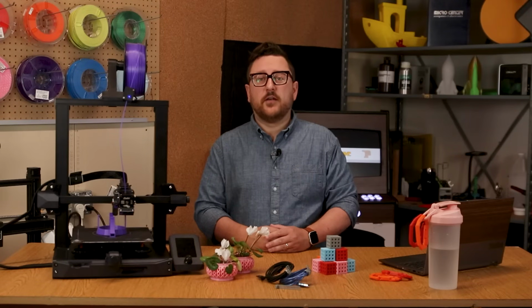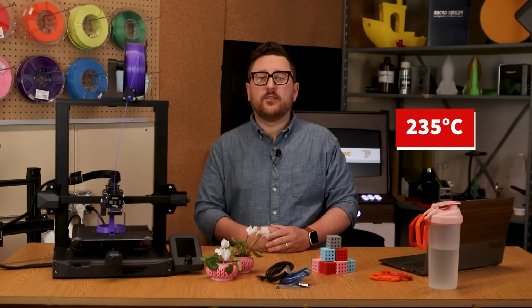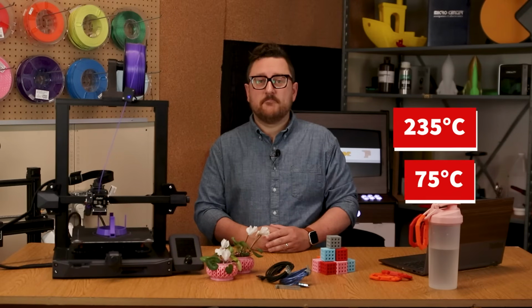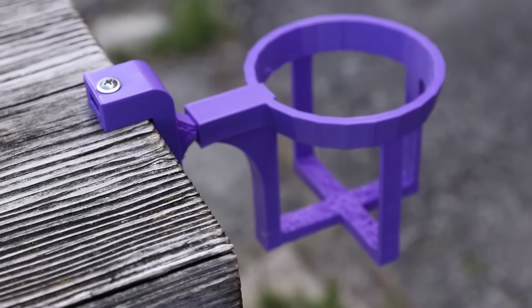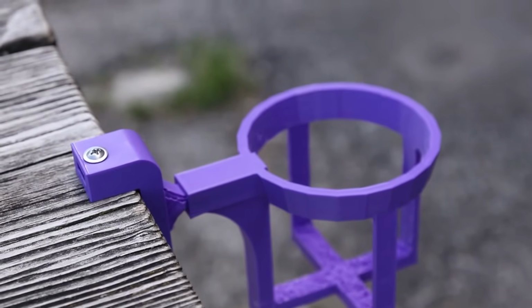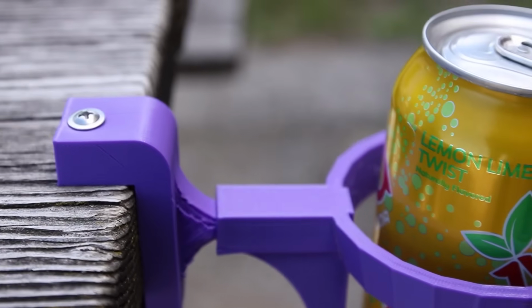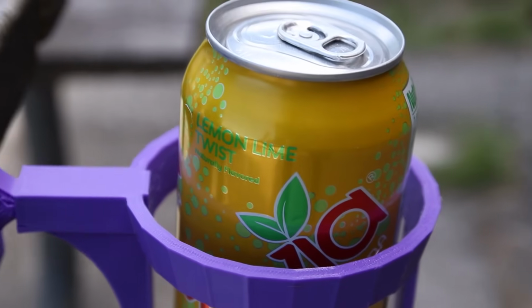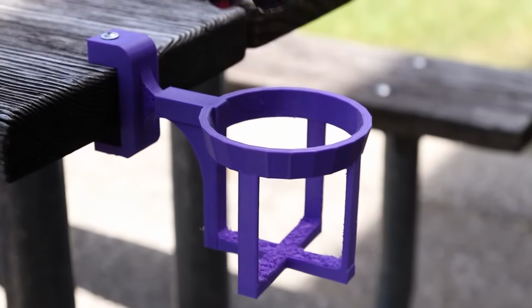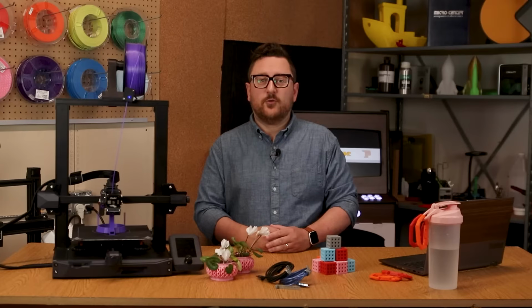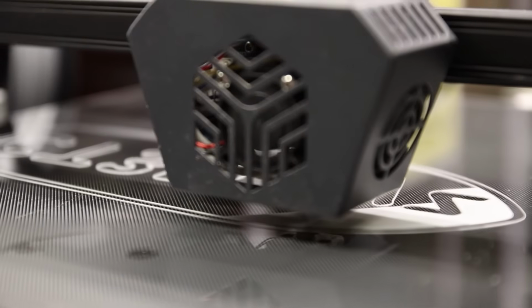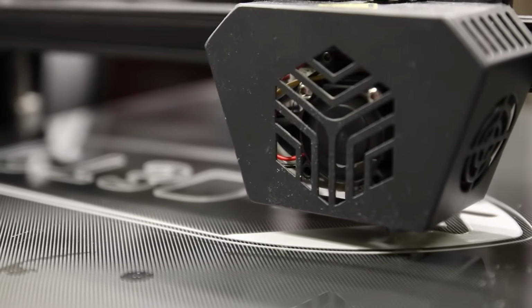For the print temperature here, we ran it at 235 degrees Celsius for the nozzle and 75 degrees Celsius for the bed. The print we chose to feature here is a clip-on cup holder. Again, the benefit of PETG being its higher durability and strength compared to that of PLA, as well as its ability to withstand higher external temperatures before deforming. Due to its impressive properties, if everything is set correctly, bed adhesion and warping shouldn't be an issue.